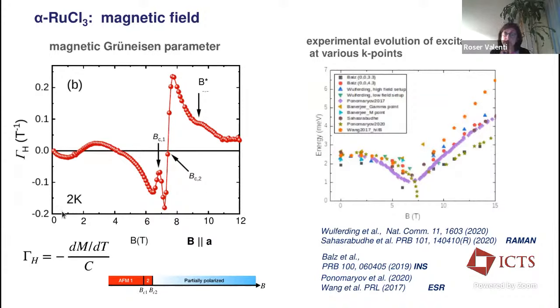And here what we see is this parameter as a function of magnetic field, precisely in the direction that so many of these groups are looking at. And there is a strong phase transition at about between 6 and 7 Tesla, which is shown by this typical behavior of the Grüneisen parameter when it hits a phase transition of second order, where you have the suppression of the zigzag order. But then there is here a little bump that you cannot identify as a phase transition, so the system is basically going continuously to this partially polarized phase.